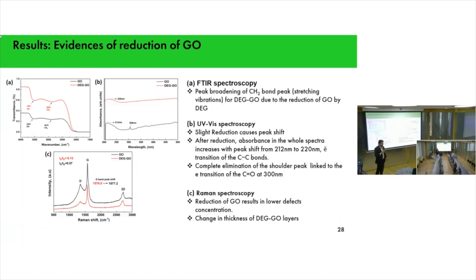So what's the evidence of reduction of graphene oxide? Our FTIR system saw a broadening in CH2 bond, whereas if you see the UV-visible spectrometry, for the simple graphene oxide, you see there are two peaks, at 230 nanometer and 300 nanometer. This one is the electronic transition from pi bond to pi star transition for the carbon-carbon bond, and then you see there is a transition of the carbonyl bond at 300 nanometer.